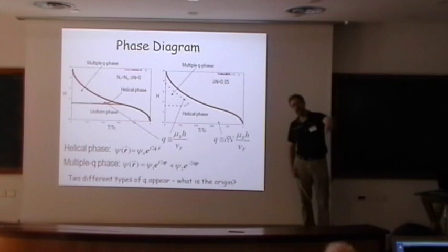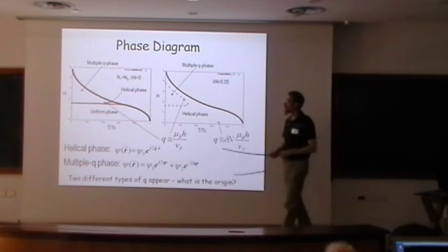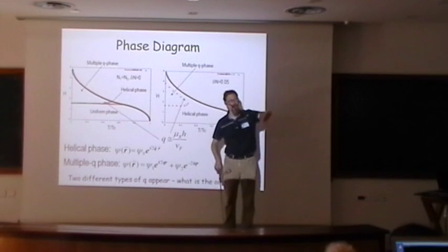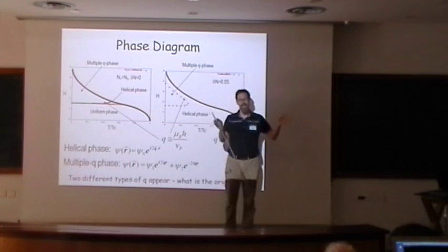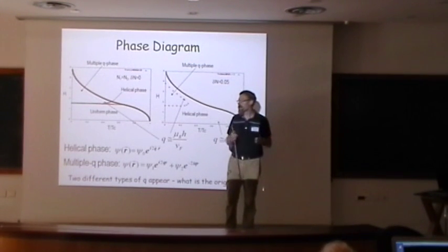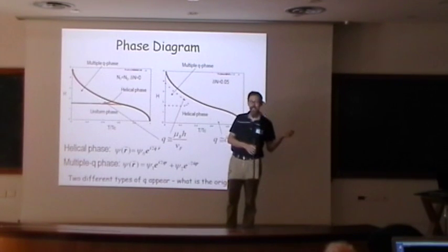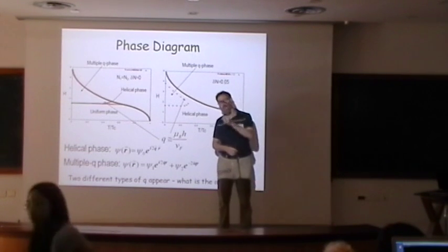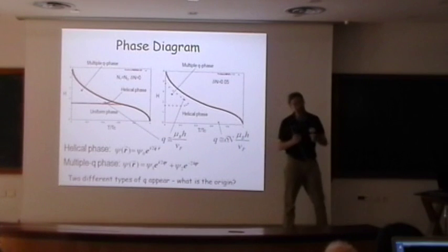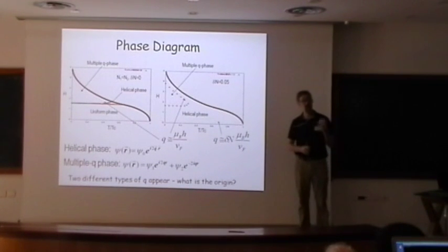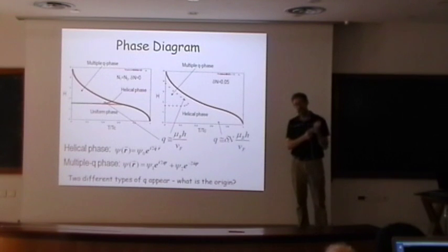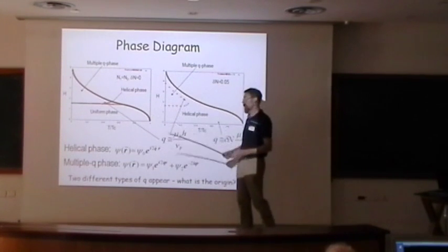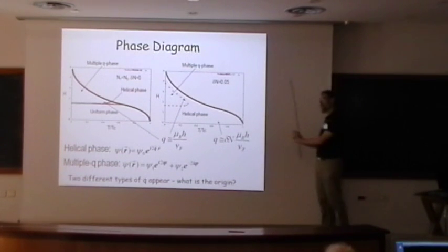You ask where is the rest of the phase going, and it turns out that what happens is, in these phases, you actually develop a periodic lattice. And if you know anything about periodic lattices, you can have dislocations as topological defects of these periodic lattices. What happens is, in fact, you're introducing half a dislocation, which gives you an additional sign change of pi, together with a half vortex, which gives you a phase change of pi, and so the total change is in fact 2 pi. So it's a combined defect, which is a mixture of a dislocation of the usual translational symmetry breaking and the vorticity of the usual superconductivity. So in that sense, it's different, but yeah.